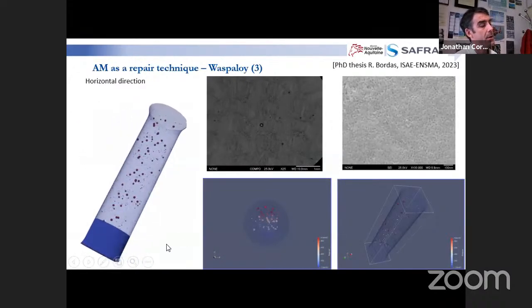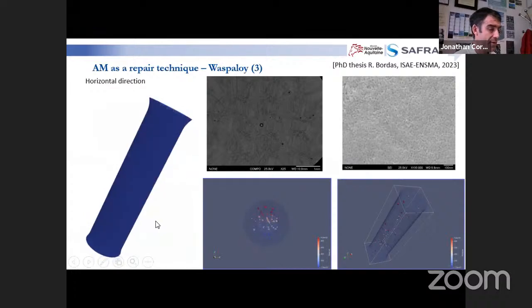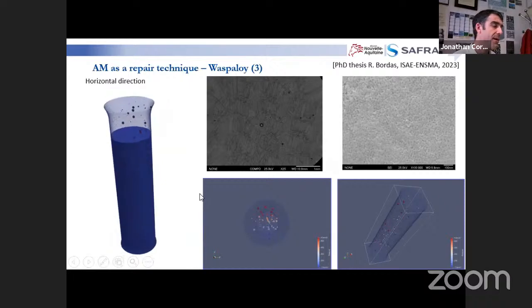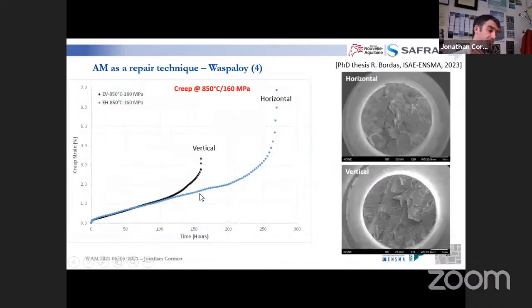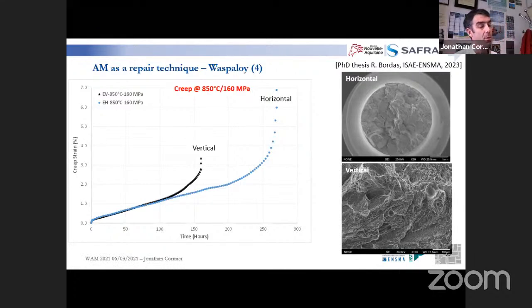What we are doing is characterizing all the specimens by X-ray tomography, to be able to correlate to the subsequent properties, tensile, fatigue, and creep ones. I just want to show you some creep properties at very high temperature, 850 C, 160 MPa. For vertical direction and horizontal direction, there is weak anisotropy in terms of primary and secondary creep stage, and we just have an earlier onset of tertiary creep in the vertical direction, which is mainly coming from the spatial distribution of the pores, which can trigger earlier onset of nucleation of cracks at specific grain boundaries in specific sections. And this is something we are understanding from the pore size distribution and spatial distribution within the build.